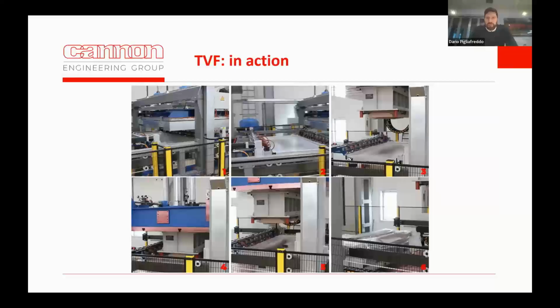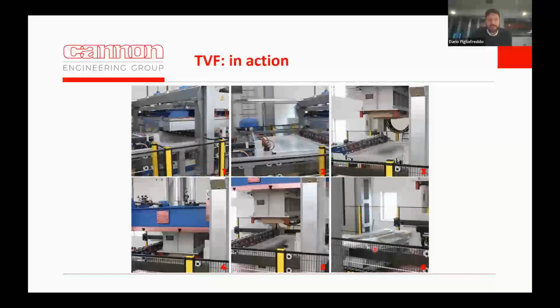These are some images to better understand how it works. From the left, we have a compact oven, which is heating up the material and the thermoplastic film. We have a transferring phase in which we bring the material under a preforming press, where we will have a tool. We will have the preforming phase under the tool, and then simply we demold and move the grippers back to the first phase. The film contains the material for a second stage, protecting the material, and you can just peel it off manually when we have to use the prepreg preform for the second stage.